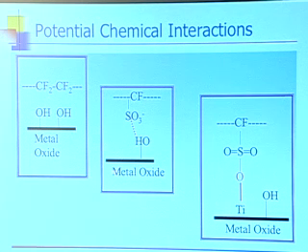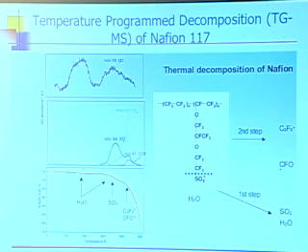And by the way, if you actually do a titration of these surfaces, you find out that typically for these systems that work well, you lose about 3% of the protons from the Nafion protonating these surfaces. And that's why the conductivity drops off a little bit. And if you happen to have a metal oxide, such as alumina, where you lose a lot of protons, that is a strong acid-base interaction, then you get a poor MEA when you make it. So this doesn't seem to make chemical sense at all, so we only have to consider the other two.